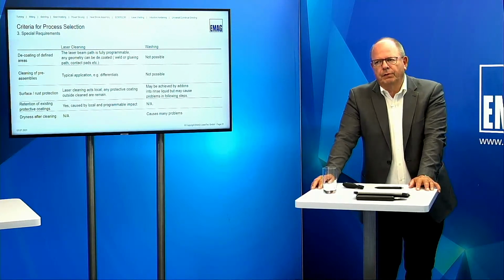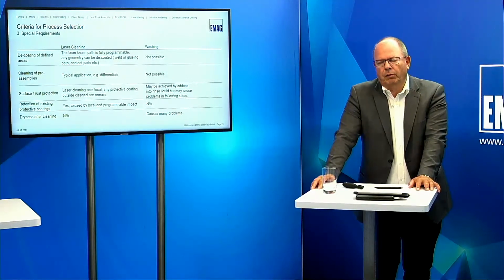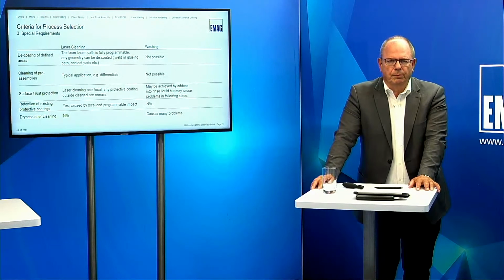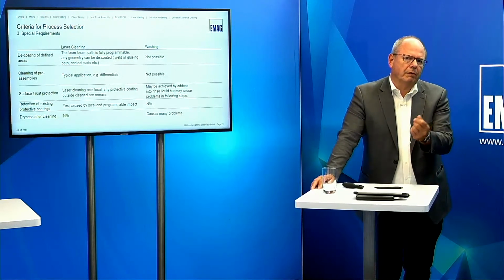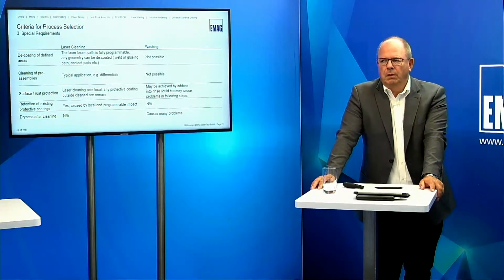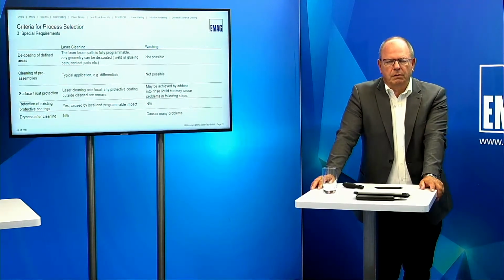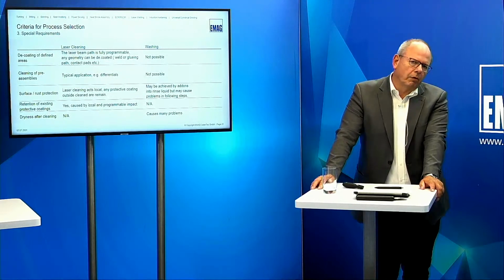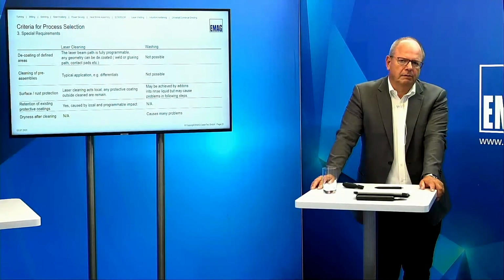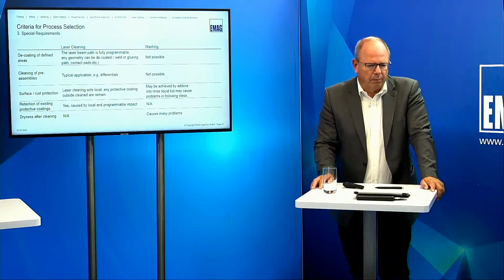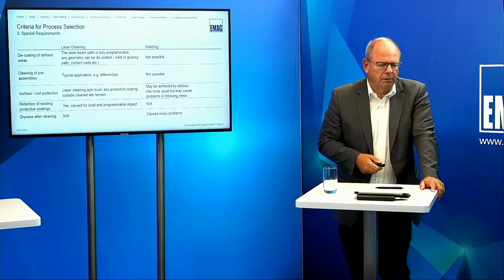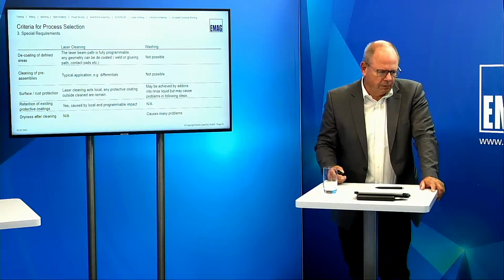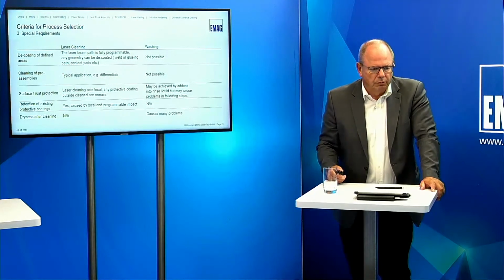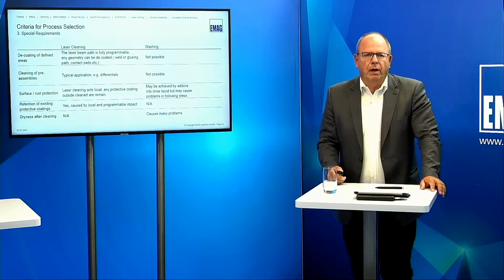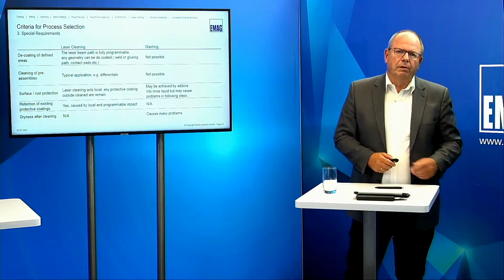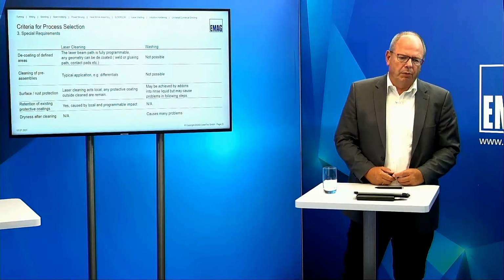This has also an impact if you think about rust or corrosion inhibited parts, corrosion protections, because you remove only in the process zone for the downstream process, let's say for gluing or for welding, the rest of the part remains untouched. If you have a corrosion protection there, you will have it also after that gluing or welding process. This can be an advantage depending on the local action, and you retain this. And dryness, I addressed this already in the beginning. This is absolutely no issue with laser cleaning, but it can be a nightmare with a washer.